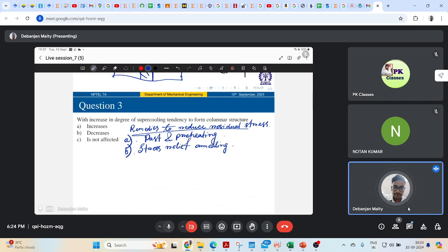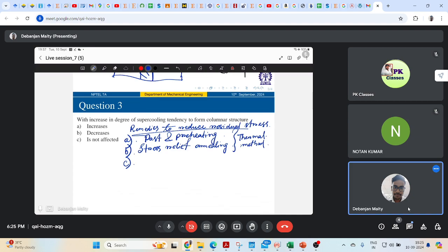It will allow your atoms to rearrange and relax your internal stresses, if there are any. These are, let's say, thermal methods, the heat treatment methods. Any mechanical methods through which you can reduce residual stress? Just a minute. If we decrease the thermal coefficient of expansion, it will lead to a decrease in residual stresses. Alpha, the coefficient of thermal expansion. That is a material property, right?